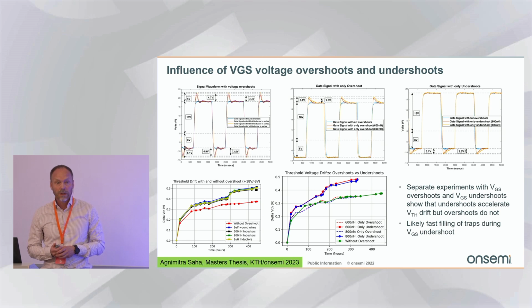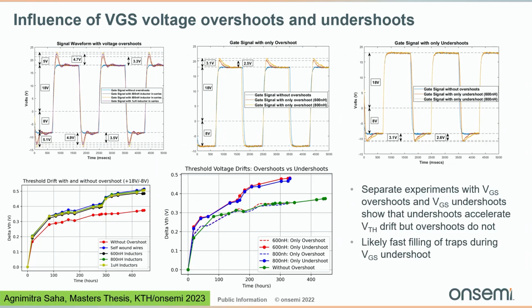And then Agnimitra also looked into when you're switching, you always have some parasitic inductance, so you can get some VGS overshoot and undershoot, and how does that influence? So he measured with both overshoots and undershoots to the left, and in the center with only overshoots, selecting the inductance, and to the right is only undershoots. And the conclusion is that if you have an overshoot and undershoot, you get more drift in threshold voltage. But when separating, it is actually the negative VGS undershoot that is accelerating the VTH drift. So yeah, there's likely some filling of hole traps fast that is happening. And that's important to watch out for, the negative VGS undershoot.